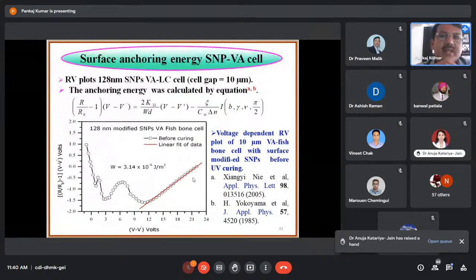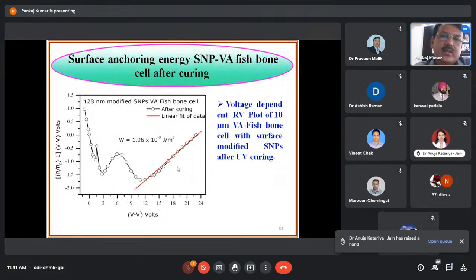Again, surface anchoring energy was performed for this cell also. The same method we have used, and you can see here the anchoring energy is in the same order, and this anchoring energy is 3.14 × 10^-5 joule per meter square. In the next slide, after curing, the anchoring energy is 1.96 × 10^-5 joule per meter square. So anchoring energy is also in the same order.